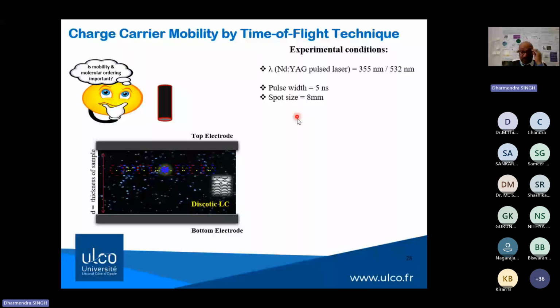Here we have an Nd:YAG laser of wavelength 355 nanometer and 532 nanometer. We need different absorption bandwidths of these laser lights, because this light should be absorbed by the material in order to release the exciton, electrons and holes. And obviously the pulse width and spot size you can change. For example, if we take a discotic liquid crystal material which is semiconducting in nature, and fill it in between your top electrode and bottom electrode, you have to fix the thickness of this device, and this thickness should not be less than 2 micron.